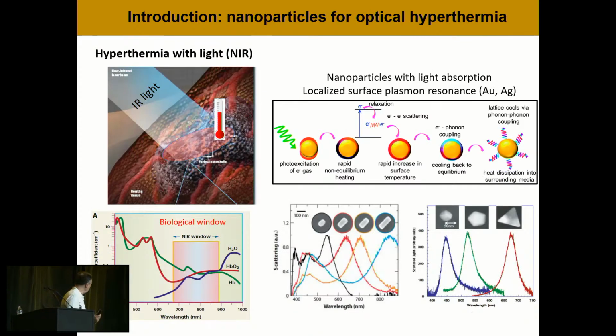So what's this photothermia? As the first plenary speaker, Luis Marsan, told us, gold nanoparticles have a plasmonic resonance. What it means is that when they are irradiated with light, they create an electron cloud that fluctuates. And when we get the resonance of these fluctuations, there is a big absorption of light in the nanoparticles. And shown here are the absorption peaks. And this resonant absorption depends on the size and the shape of the nanoparticles. And we can tune the wavelength at which this absorption takes place.